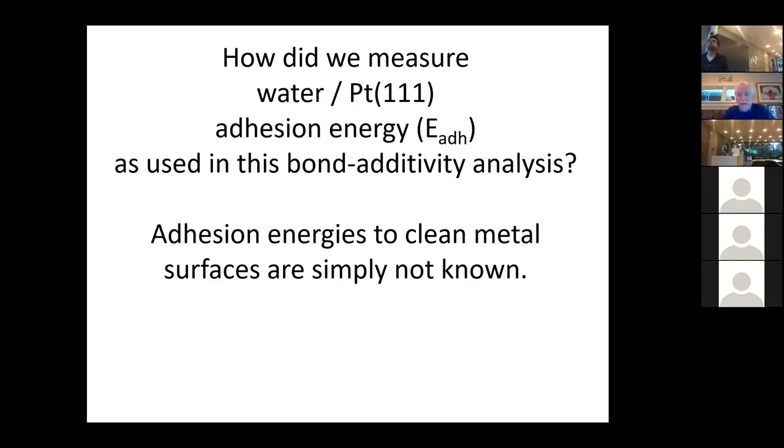Calorimetry had been done in the aqueous phase, and the heat we got out of the CV measurements and the approximation about the entropy came very close to the heat from the direct calorimetric measurements in the aqueous phase. But, that's an aside.